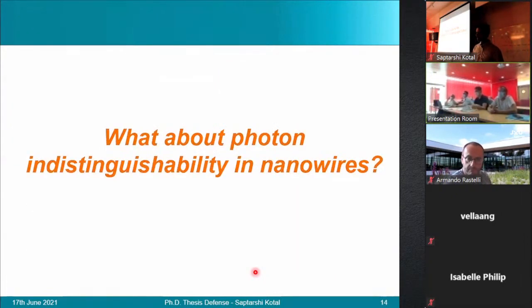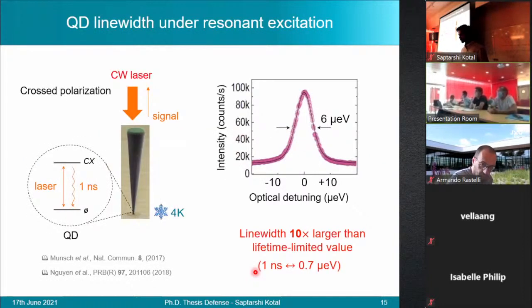Now, while nanowire antennas have enabled impressive results in the field of single photon emission, how do they fare when it comes to generating indistinguishable photons? To address this, let's look at the results that were independently carried out both in the group of Richard Warburton in Basel and the group of Jean-Philippe Poizat here in Grenoble. So the quantum dot transition was resonantly excited with a spectrally thin laser, and in so doing, resulted in the following spectrum. Now, as we can see, this spectrum exhibits a 6 microelectron volt line width. Now, mind you that a quantum dot in this system would have a radiatively limited line width of the order of 0.7 microelectron volts. That means the measured line width is almost 10 times larger.